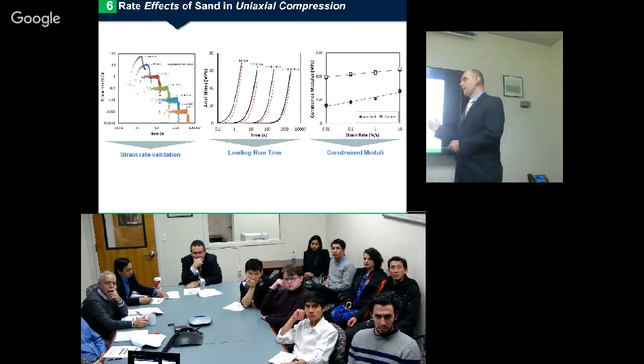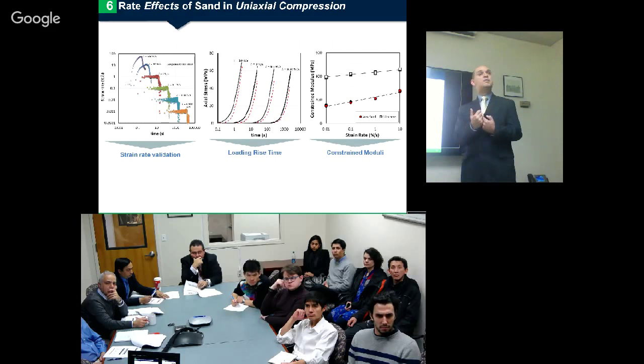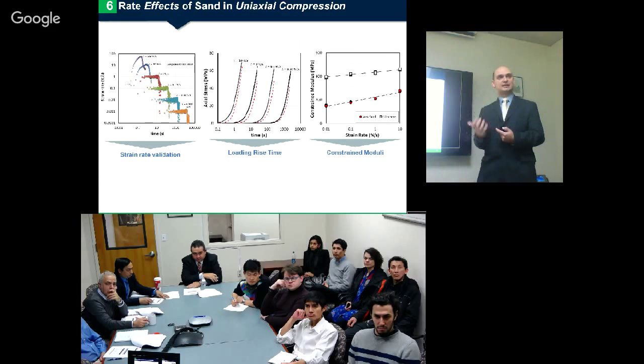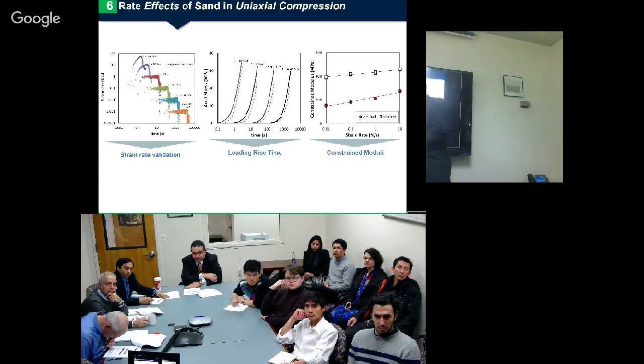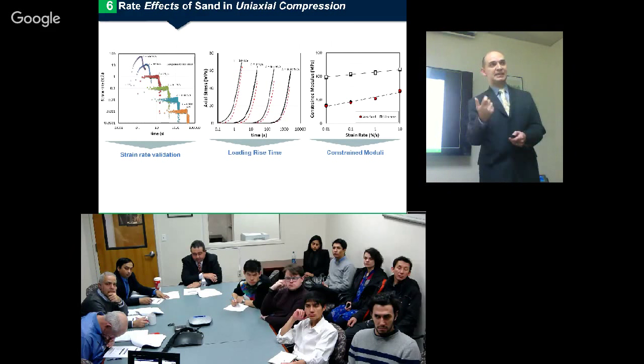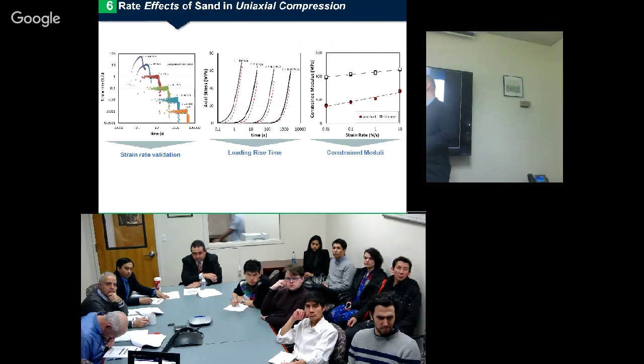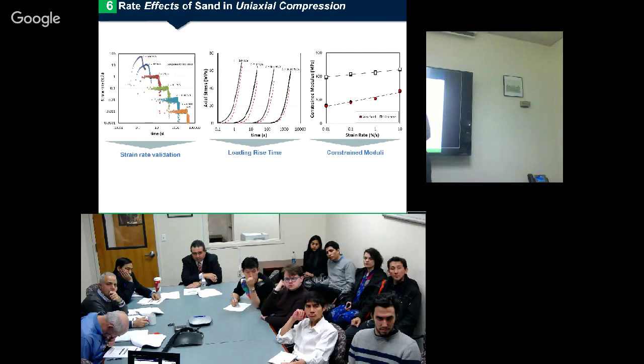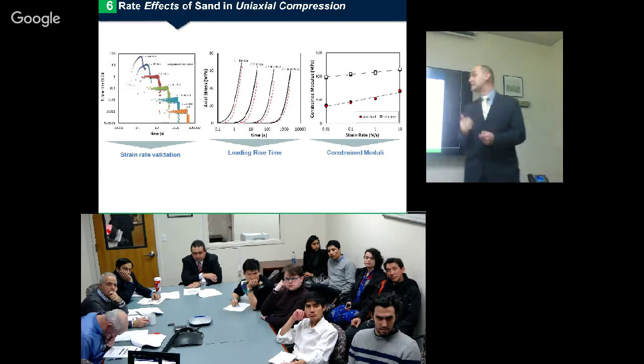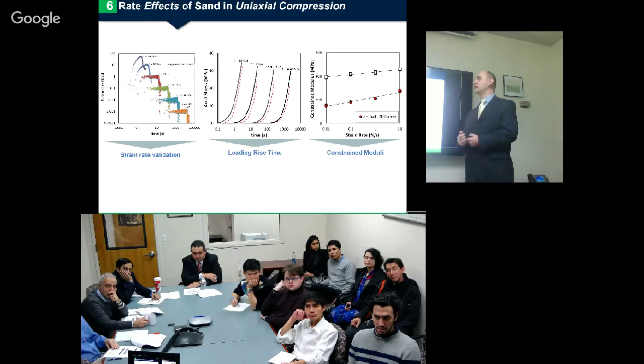I also ran a few verifications to check that the strain rate that I targeted with my samples were really experiencing these strain rate conditions. So you have the time, again, the target strain rate. By doing the calculations, I was able to check that this strain rate here is constant for this, for this, for this, and also for 10% per second. The steady condition of the loading for this small period of time was achieved, whereas for 100% per second, which is a limitation of the device, this curve didn't reach to this point. That's why I decided not to use the hydraulic machine to run tests at 100% per second.